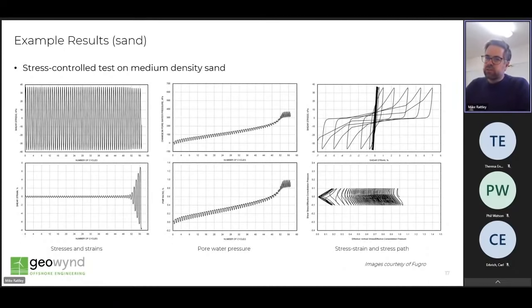Shown on this slide are the results of a stress control test on a medium density sand, relative density of around 50 to 60%. Strain accumulation is very limited until the effective stress essentially approaches the zero point, so that's the initial liquefaction point that Carl mentioned earlier, at which point large strains are accumulated on subsequent cycles, albeit in this case tempered by that dilation which occurs at large strain. So this indeed is not an example of a flow liquefaction failure, but more a mobility failure, but with a soil that doesn't have a tremendous capacity for dilation, and therefore induces large strains accumulated on each subsequent cycle.